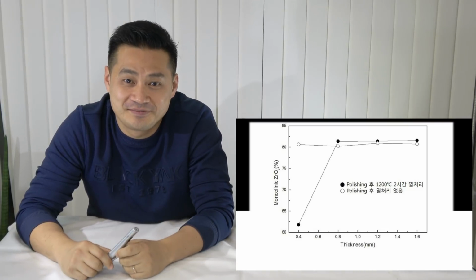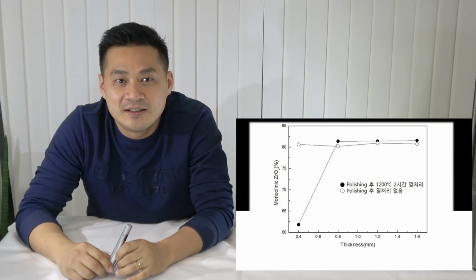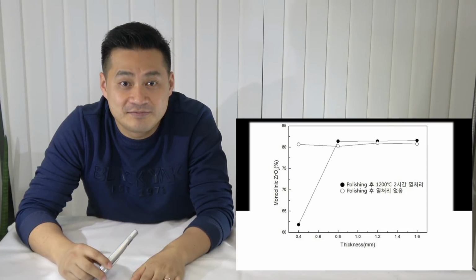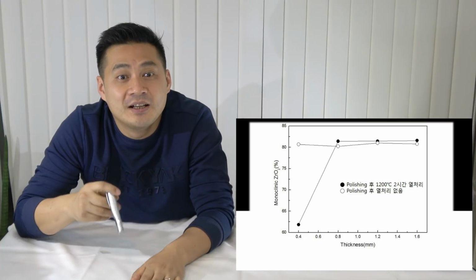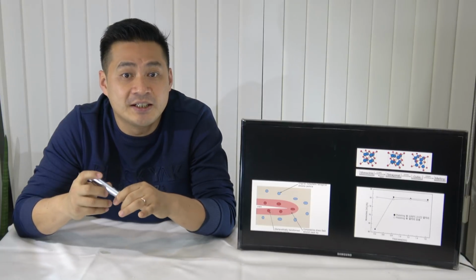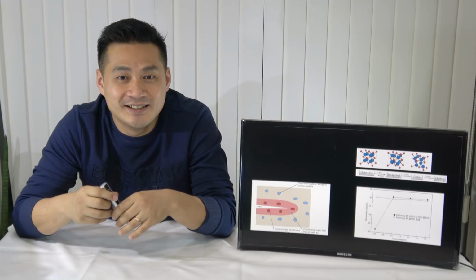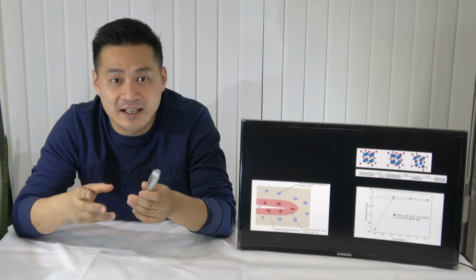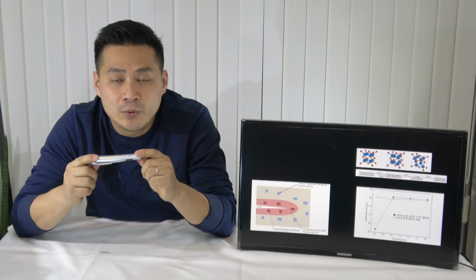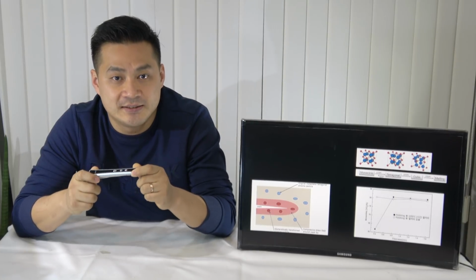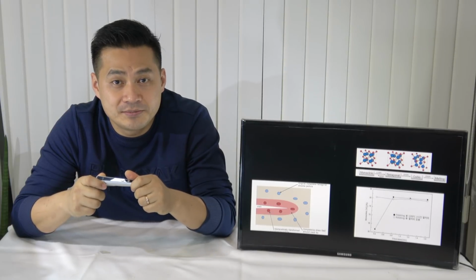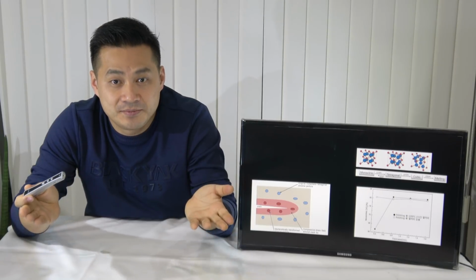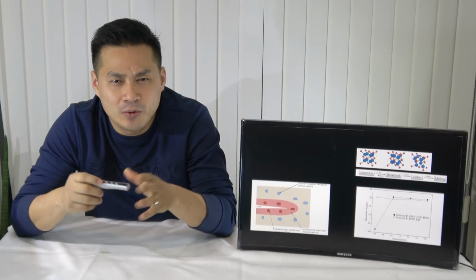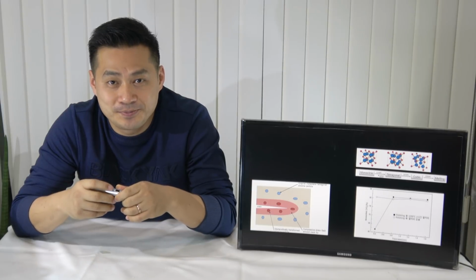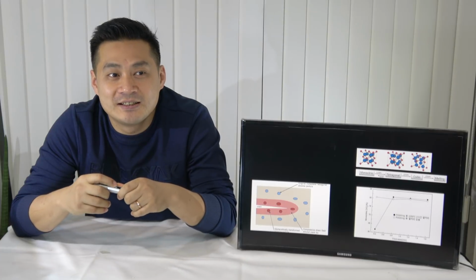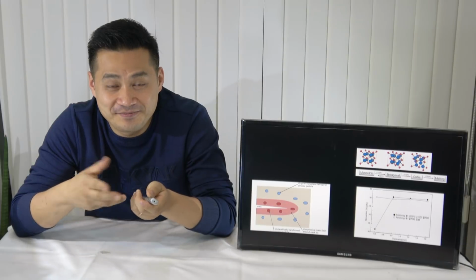Look at the results. Zirconia with more thickness has not changed. What happened to this zirconia? Even its black monoclinic rate increased compared to white. So why? I think it doesn't get enough heating. It means we should use a different temperature for each thickness. What do we do? Nothing. Do not reheat zirconia, because we don't know the correct temperature for zirconia. So please don't reheat zirconia, okay? That's my opinion. If you want, try.